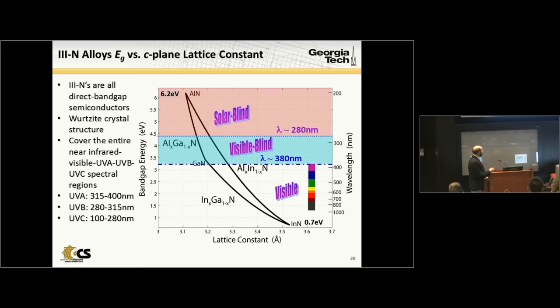And these are not visible to us because the human eye response begins around 380 nanometers to about 900 if you're lucky, maybe 800 nanometers. So this quaternary system is unique. It's all direct band gap, and it gives us access to virtually all the photons we need for most of humans' activities, and even things that we haven't yet invented, perhaps. So it's quite remarkable. It has lots of challenges, and Jiahong's going to solve most of those here at KAUST, so you can look to him for the solution for these problems.